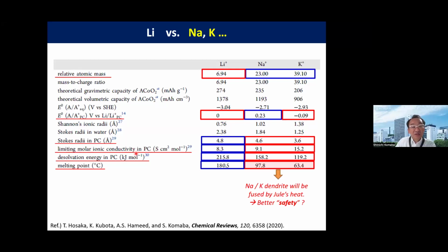And the ionic conductivity, that is, the limiting molar ionic conductivity in propylene carbonate, is higher for potassium and sodium than lithium. The desolvation energy, especially in the interfacial process, should be a much lower barrier for sodium and potassium compared to lithium. Melting point: yes, lithium is the highest among these alkali metals.